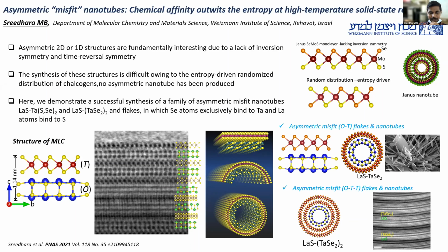But a single layer of 2D molybdenum sulfur selenide has been produced by ion implantation, by selectively removing the sulfur. What we present here is a way to synthesize such an asymmetric structure using misfit layered compounds composed of lanthanum sulfide and tantalum disulfide. We replace the sulfur with selenium, and we see that selenium exclusively goes to the tantalum and sulfur goes to the lanthanum. So fundamentally we outwit the entropy using the chemical affinity in this compound.